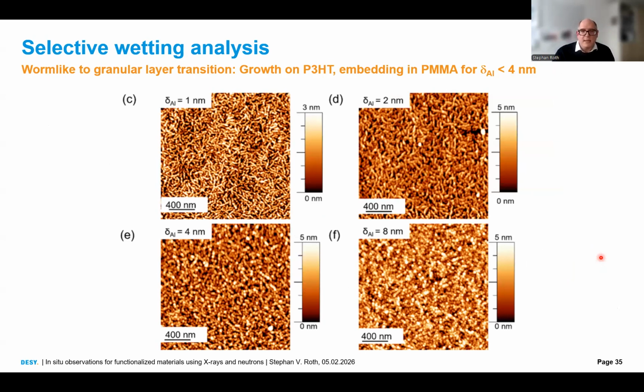electrode. And then if we look with AFM in more detail, you can really see here, when you put a little aluminum on, you see these are P3HT domains. They always have a worm-like structure. You see here clusters growing on these worms. You see it here even better at 2 nanometer. They become very large at 4 nanometer, and at 8 nanometer, you lose this worm-like structure, meaning that now the aluminum indistinctively grows on both of the domains of the diblock copolymer.